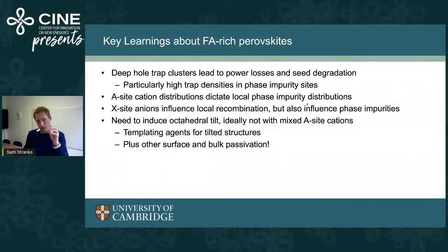I haven't shown it today, but we do have evidence that the X-site, the halides, also influence it, although it's much more complicated, and we're trying to understand how the halides influence the phase impurities as well. But a key take-home is that we need to induce octahedral tilt, so we need these formamidinium-rich samples to be slightly tilted, but not with mixed A-site cations. This means exploring templating agents to tilt these structures without additives. In fact, there have been some reports in the literature where this seems to be happening, at least serendipitously, in these formamidinium-rich samples. And we are starting to see evidence that these are also tilted in phase.